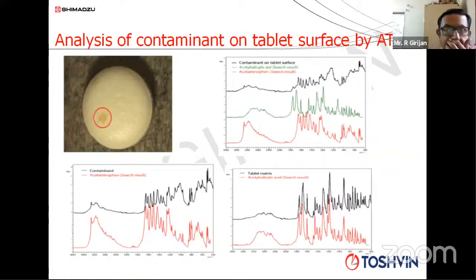This is a typical example of another ATR application, a contaminant on a pharmaceutical tablet. After manufacturing a tablet, on the left-hand side, you can see there is a red circle. A slight yellow patch is shown, and we have circled it in red. We do not know whether it is an external impurity sticking on the tablet, or something that has come from the formulation itself, maybe because of improper mixing and blending, and has come out on the surface and segregated. We want to know whether it is an external impurity or something internally present that has segregated on the surface because of improper blending and mixing.